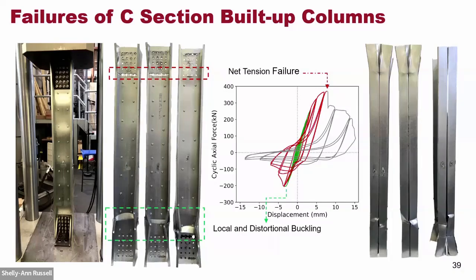So this is local buckling of the web. When we apply the loading, this elastic buckling happens several times. But after a certain point of this green line, you can see this buckling happen here. With continuously applying more cycles of loading after these points, the damage accumulated here, and the inelastic buckling started to appear here with these elements, and for the third was here. And after this point, we had net tension failure at these fastener holes with the hold downs, and suddenly this point decreased to this point. Also with this damage accumulation, you can see there was tearing of these rounded flanges of these webs in all of these three elements.